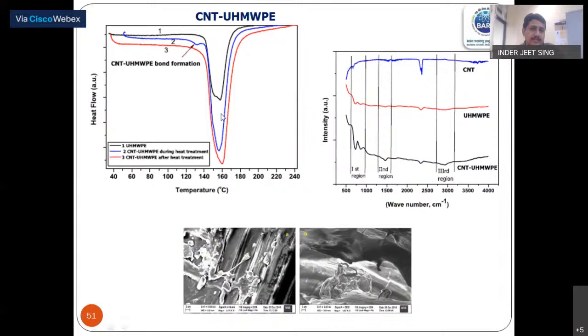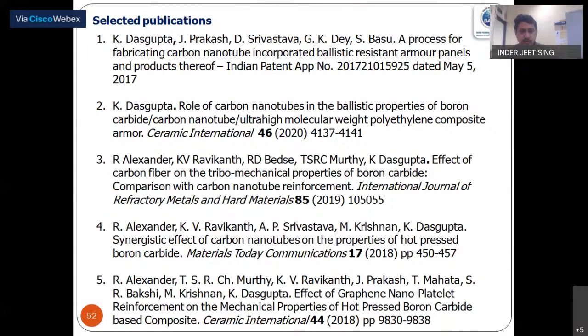So this is a DSC, differential scanning calorimetry, where it shows that there is a bond formation between CNT and ultra high molecular weight polyethylene when they are processed up to a particular temperature. And even in the microstructure, we can see the carbon nanotubes between the layers, which really makes the ultra high molecular weight polyethylene a very stiff material. So the selected publications are shown here.